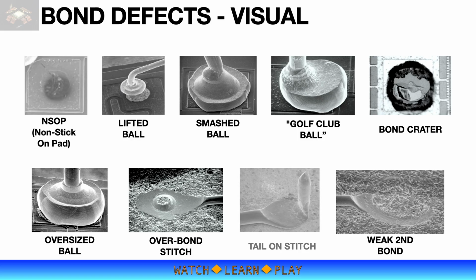Tail on stitch is an indication that the wire after the second bond is not breaking properly. This can be due to the second bond being too light, as shown in the image, which can be due to improper second bond parameters. Also, different lead frame or substrate lead finish will result in different surface hardness and usually requires different second bond parameters. The last image on the bottom right is a weak second bond defect.